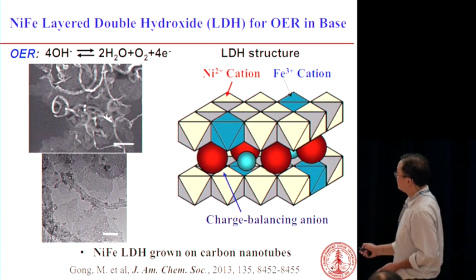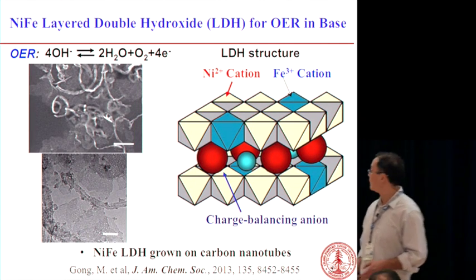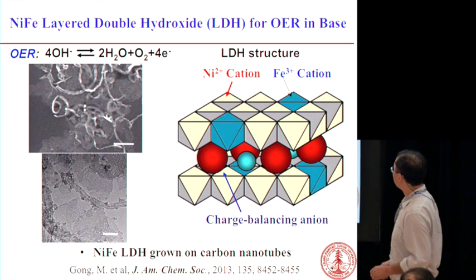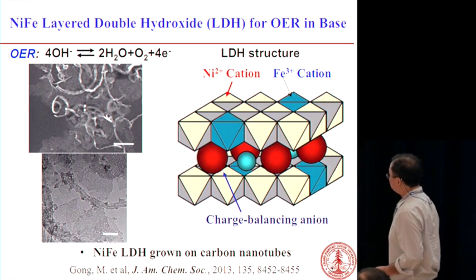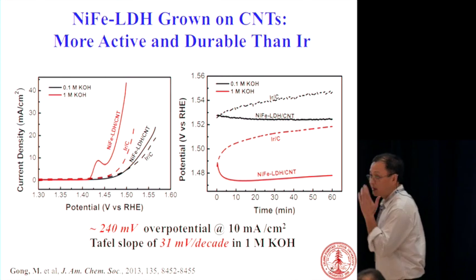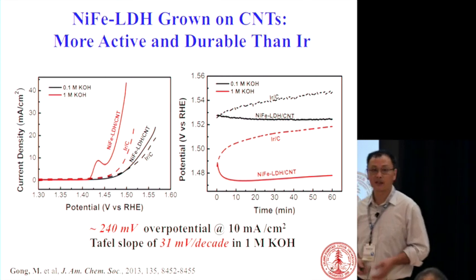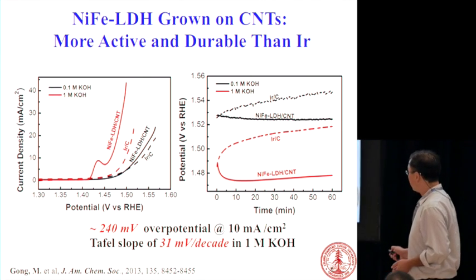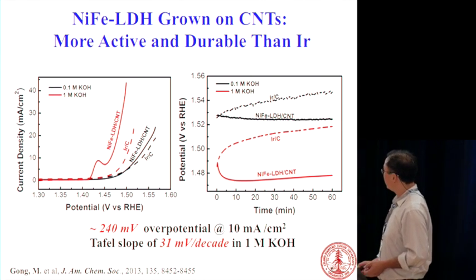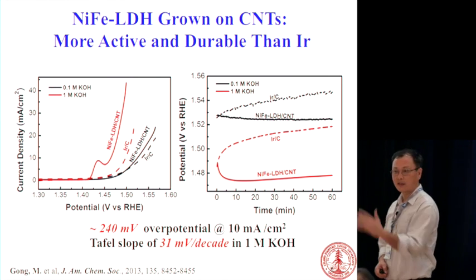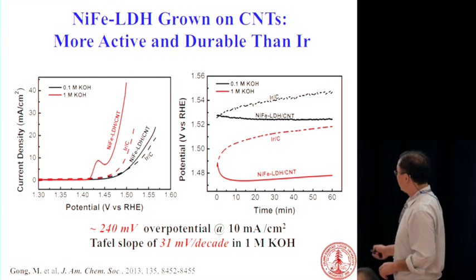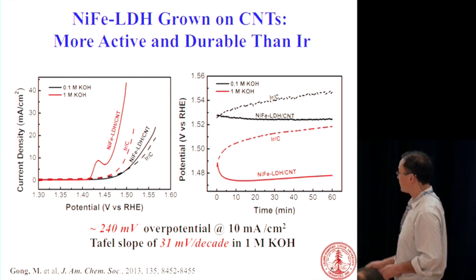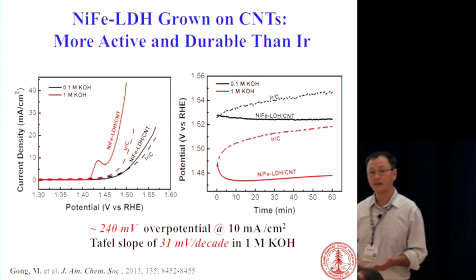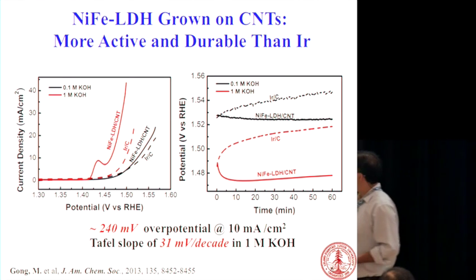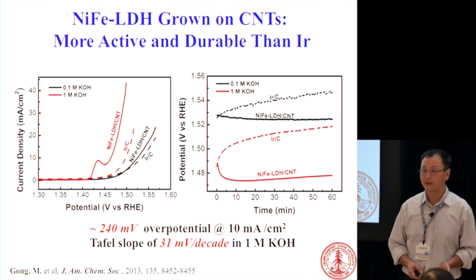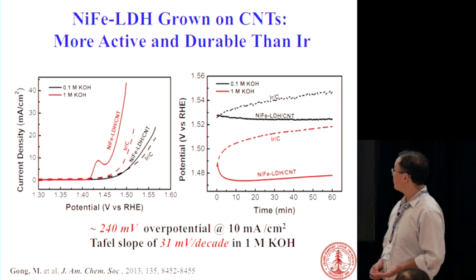So they would look like this. Okay, the nanotubes are wiggly, and you have these very thin plates sitting on the tubes. And now if you look at the activity to produce oxygen, it's actually quite good. So the red curve here is the current associated with oxygen production. And you can see the voltage needed is actually lower than iridium. Okay, iridium is the gold standard for OER. It's more active than iridium in basic solutions.